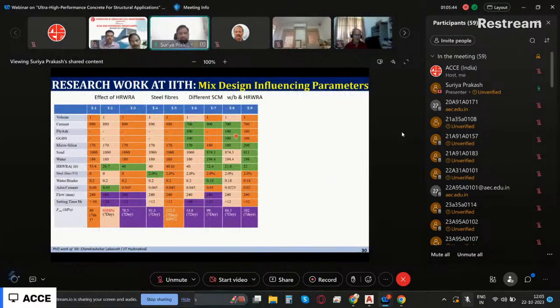So, optimization of mix design that I talked about is also going to play a major role. This is the PhD work of one of my students. And you see here, in the first trial we did, we used cement of 890. I'm just giving some numbers, microsilica and so on. But you see the strength we are getting is only about 40 megapascal. And setting time is also more than 40 hours, which is not good. And flow, though flow we are achieving.